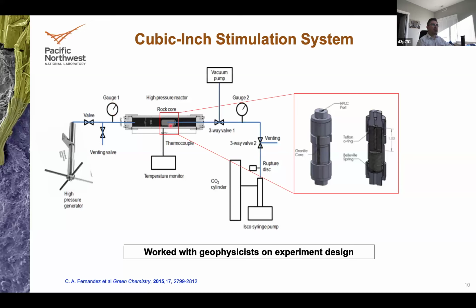That means you have a fracture connected. These are diorite samples or Newberry samples. We did multiple of those. And when you fracture, basically you have a connection between the wellbore and the walls of the sample. This sample is close to 1 inch in diameter by 2 inches in length, very small samples.